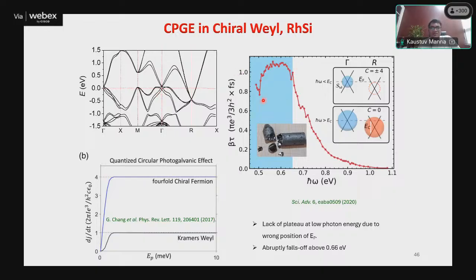But when we do the experiment, what we observe is that there is a little bit of frequency dependence. And when you cross this energy, linearly more and more electrons start to be excited, so the DC current will nullify and fall. So we observe the trend, but we do not observe the quantized flat value that we expected. The reason is that there is a flat band. This flat band also gives excitation, first thing. Second thing is that this excitation energy matches with this trivial band gap. This value and this value are almost the same.